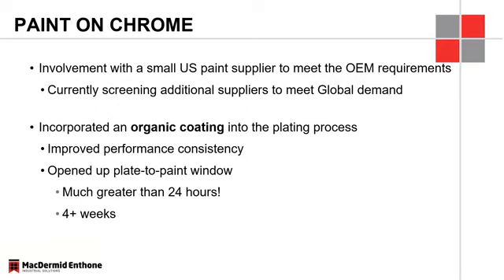But there are some OEMs that have a 12-hour, 24-hour window between the time those parts come off the plating line and when they need to get into paint. As a result of incorporating this organic coating into the process, we've been able to open up that window to as much as 4 weeks or more. So parts can get plated, they can sit for 4 weeks, go into the painting process, and still have exceptional adhesion and pass these OEM specifications, only with the incorporation of this organic coating.